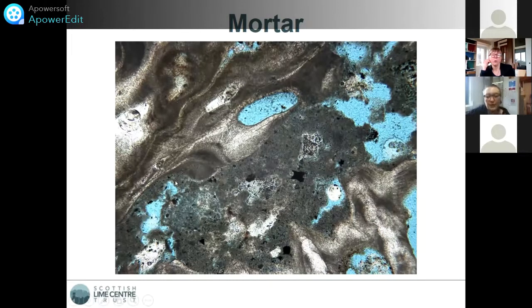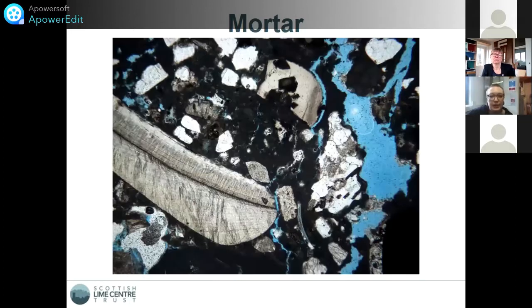So something that's really important when you're looking at mortar is understanding, obviously, your mix proportions, but also what your aggregate is, what the texture of that is, what is its composition. And because it had shell fragments in it, and they're of marine origin, you can make a guess that this sand probably came from the mouth of a river or from the beach. And more images here. This one is showing a really, really beautiful shell fragment, and this will be from a type of animal called a bivalve.